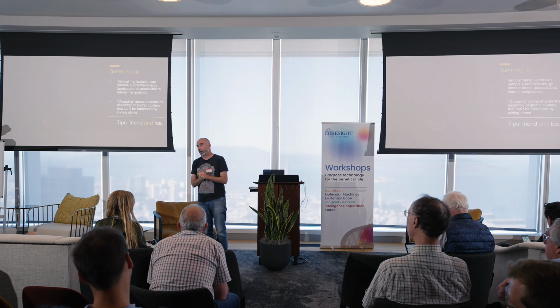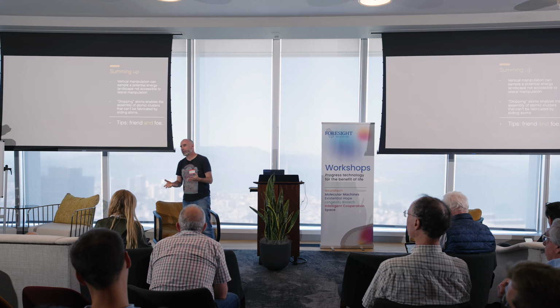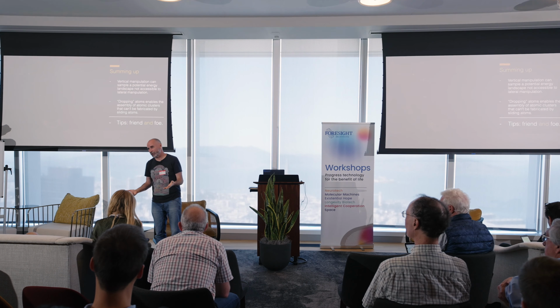What you can do, of course, is what Rezo talked about: you can inject a current and vibrationally heat up a silicon-hydrogen bond, for example, up to the point where that atom pops off and desorbs that way. But there are a number of examples where, in fact, in many cases with STM, you end up picking up atoms or molecules when you don't want to.